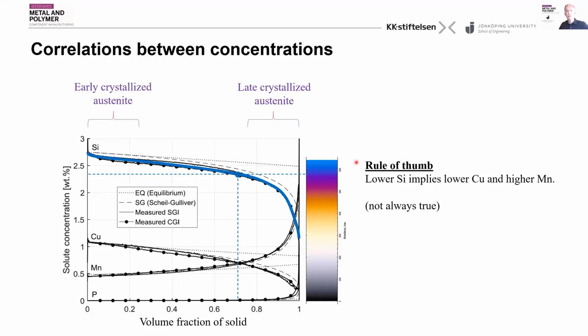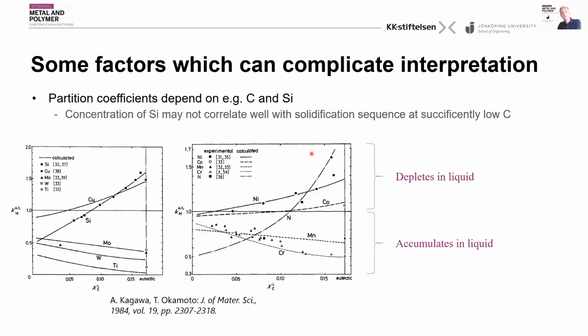And as we said earlier, which maybe is emphasized in this graph, the silicon concentration also correlates quite well with segregation of other elements. There are, however, some factors which make the segregation patterns, which you see with the color etching, a bit more difficult to interpret under certain conditions.